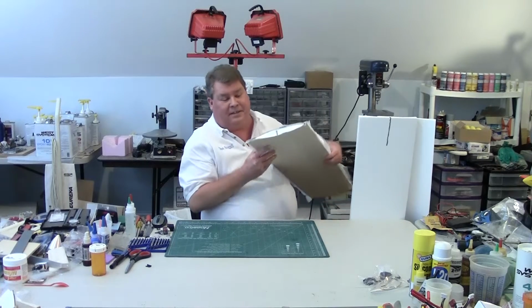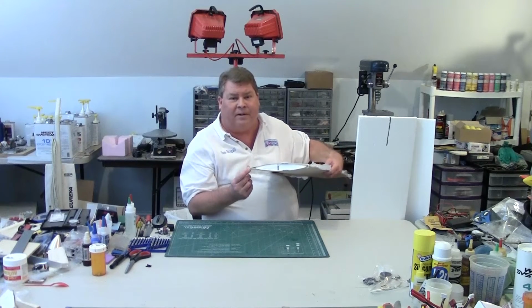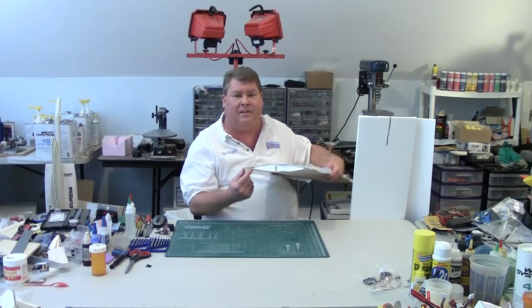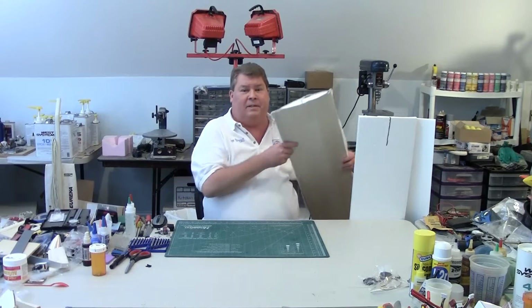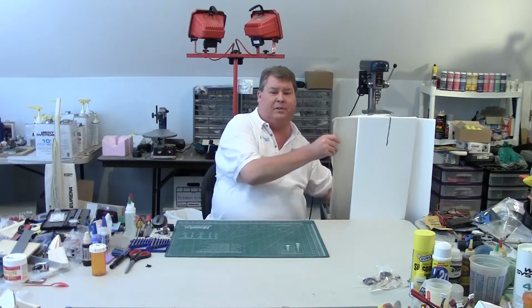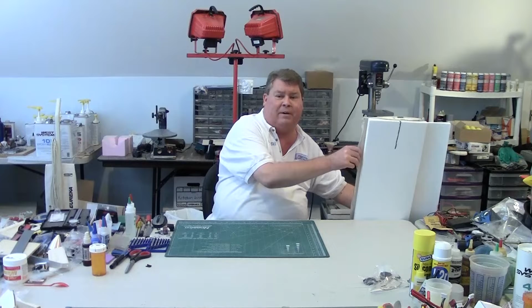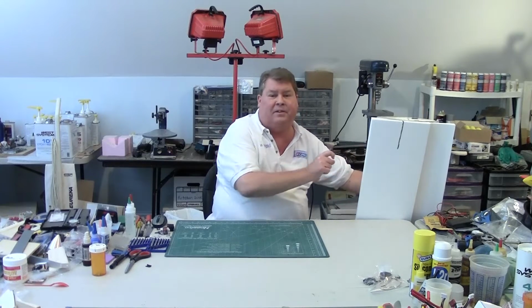One thing I've changed is that I now use carbon fiber laminate on the trailing edge. This is 5 thousandths thick and 1.5 inches wide. It extends back into the aileron and allows for sharper trailing edges than the 1/64 plywood I was using. I also used to put 1.4 ounce cloth on the trailing edge. With the carbon fiber laminate, I don't feel the cloth is necessary, and I can just use the 0.7 ounce cloth entirely on the wing skin. The laminate costs more, but I feel it's worth the extra $5+ per wing.